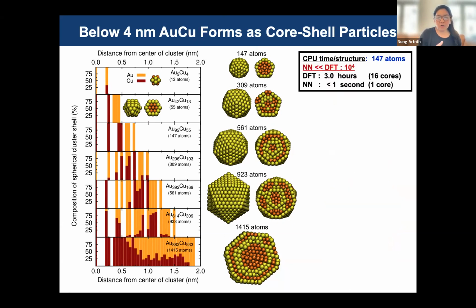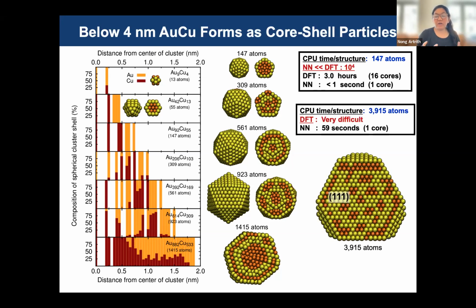But take a look at how efficient it is. Of course, our NN can already give results as accurate as the reference DFT data, but the CPU time to calculate one DFT calculation, for example with 147 atoms, takes about 3 hours on a high performance computer with 16 cores. With our machine learning neural potentials, once we have the models, we can predict one composition of 147 atoms in about 1 second. For a larger, realistic structure like this, around 4,000 atoms, it is very difficult with DFT to find the structure and really do the simulation. But with our network, it takes around 1 minute to get this energy and atomic structure.